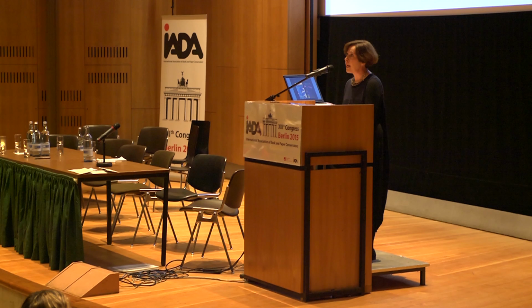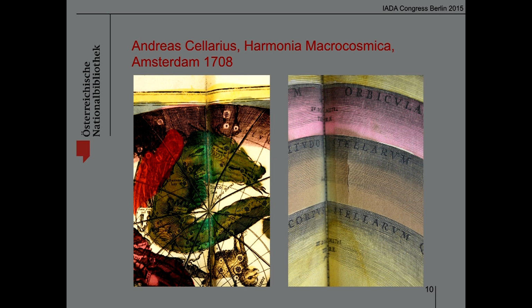In the part of the map which has been attached to the guard, the green color is sometimes protected by the hide glue of the guard and has preserved its original color. Especially areas that are exposed to more mechanical stress when the papers are turned have smaller or larger tears due to the embrittlement and the loss of flexibility of the cellulose.